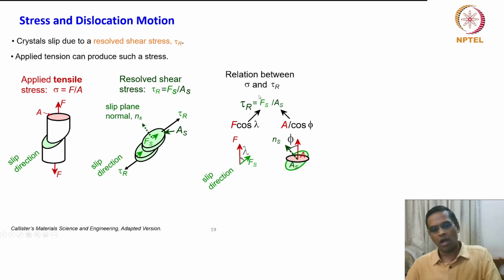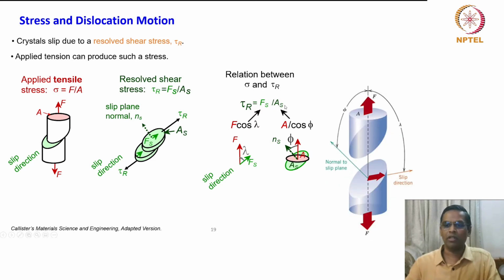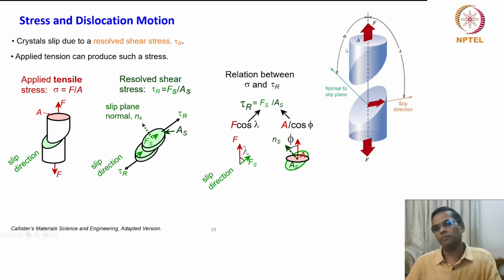And then if you look at the relation between sigma and tau R, we can further expand this: tau R is equal to Fs by As. If you look at what is Fs and what is As, for that I need to bring a more detailed schematic here. This is the cylindrical member which is subjected to slip, and then it's a slip plane, and then this slip direction, and the force is a tensile force, uniaxial force, and the area of the cylinder is A here. This green line is normal to the slip plane, which is kept at an angle of 45 degrees here, and the angle between the slip plane normal and the tensile axis is phi, and the angle between the slip direction and the tensile force is lambda.